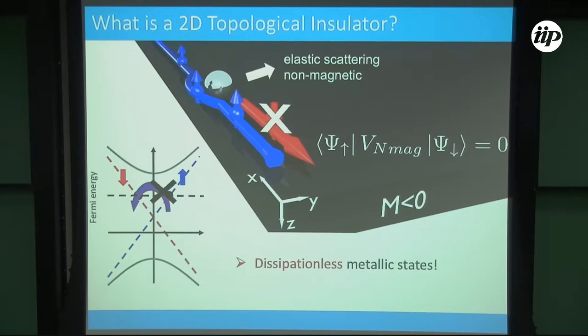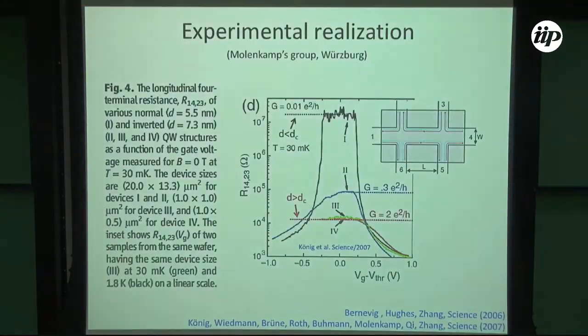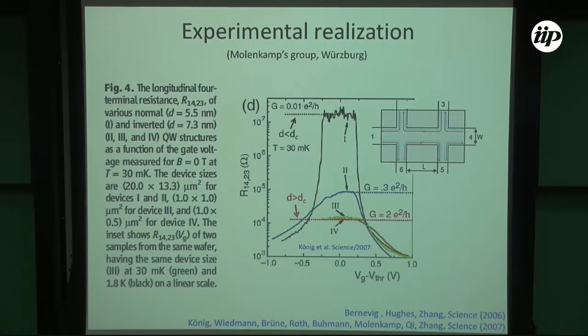It's a 2D topological insulator. For a 3D topological insulator, this protection is not as great because you have a Dirac cone on the surface and you can actually scatter via a small-angle scatter. You can fabricate a sample of cadmium telluride / mercury telluride quantum well, and in different regimes you find that the system can show topological insulator behavior. This 2e²/h is essentially counting the number of edge state channels.